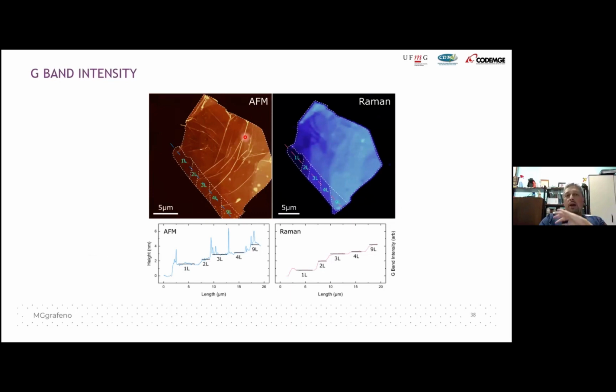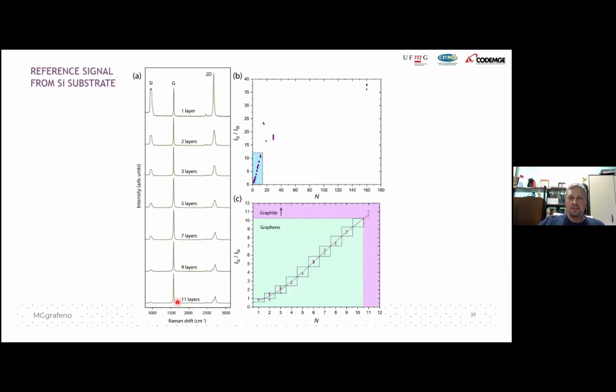So we adopt another approach, which is the G-band intensity, which just measures the intensity, okay? And we compare with the substrate intensity. And we can see here that this peak from graphene increases the ratio between the peak and the silicon peak from the substrate. The ratio increases as I increase the number of layers, so it scales nicely with the number of layers.